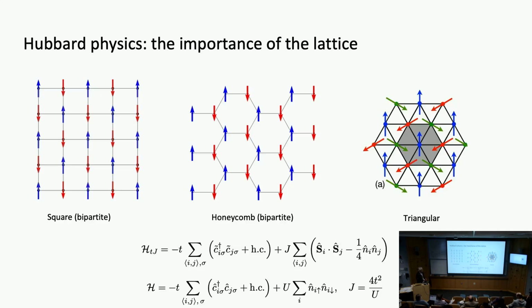This is equivalent to the so-called TJ model in the limit of large U. So the ratio of T over U is very small. This model is equivalent to this, which consists again of a hopping term and a spin interaction term. And it's this Heisenberg-type spin interaction term that produces the antiferromagnetic ordering here or here.